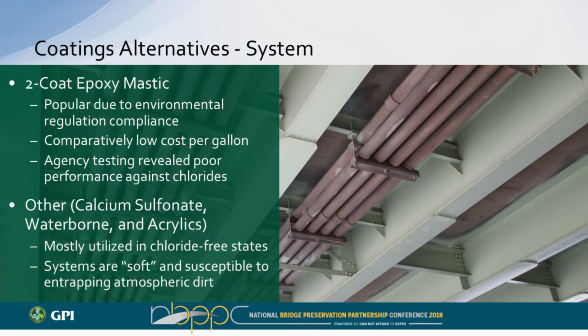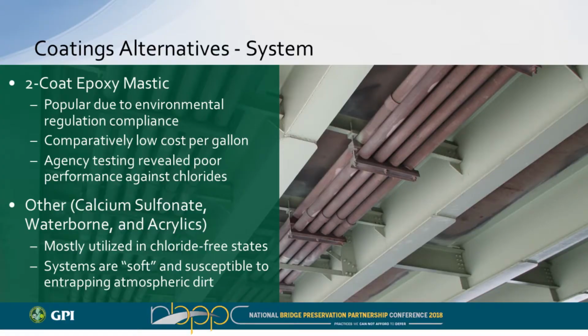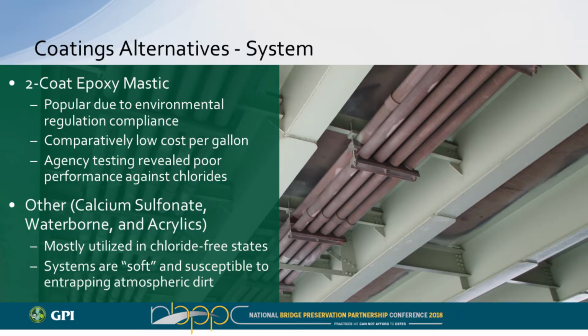All right, we looked at two-coat epoxy mastics as well. These are popular. They've got lower VOCs, so they're easier. They're much more environmentally friendly for those ever-increasing requirements. They are comparatively low cost per gallon. However, agency testing, and FHWA is actually one of them as well, tested these systems and found that they really don't have very good performance against the chlorides. And in the Northeast area, that's heavy, heavy chlorides to treat our roadways. And then we looked at calcium sulfonate, waterborne, acrylics. These tend to be utilized in the chloride-free states because they're a much softer system.